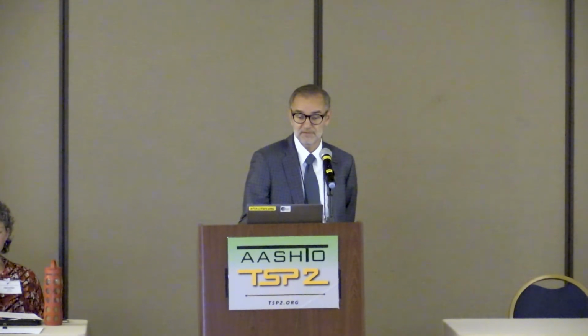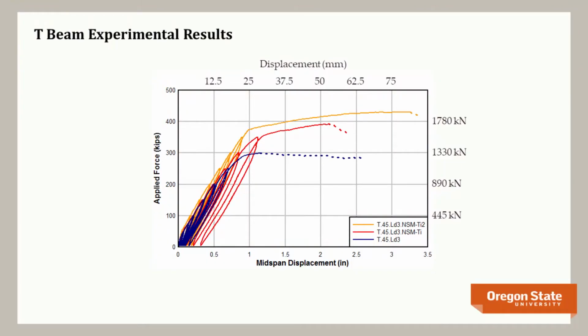And in fact, we fail it in flexure where the titanium bars end, but those steel bars are well anchored, and that's really what your intent is with a repair, is to take away the defect and force the failure into a ductile location. So the control specimen is shown in blue. We reach a peak load, and essentially it would have failed if it's a load control. Once we add the titanium, essentially we can increase the strength, and it continues to gain strength even after the steel anchorage has failed because the titanium is doing all the work, and we get very large deformation. So that large deformation essentially gives you a good sense of warning.